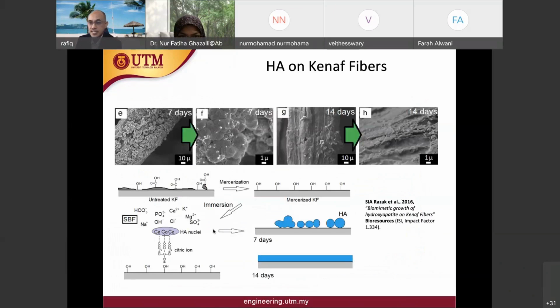And this one is on kenaf fibers. Again, Malaysia produces lots of kenaf. We have lots of kenaf fibers. One of our students, Dr. Saiful, utilized kenaf fibers and tried to see the growth of hydroxyapatite on kenaf fibers. So that's the picture of the untreated kenaf fiber, and then after mercerization, and then the immersion under simulated body fluid, and after 7 days we can see some hydroxyapatite formation on the kenaf fibers, which of course requires further research.